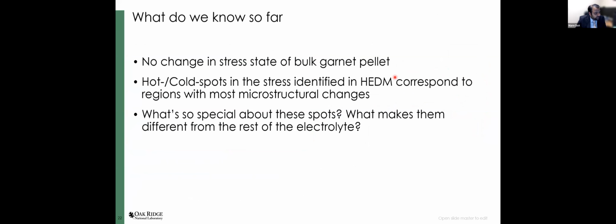So what did we learn so far? We learned that the change in stress state of the bulk garnet pellet is essentially non-existent. Almost all 30,000 grains do not show a change in stress as you fail a cell. However, the hot spots and cold spots in stress that we identified in the HEDM are the regions that show the most microstructural changes. And so we wanted to identify what exactly it is about these regions that makes them so special, that makes them high stress or low stress.